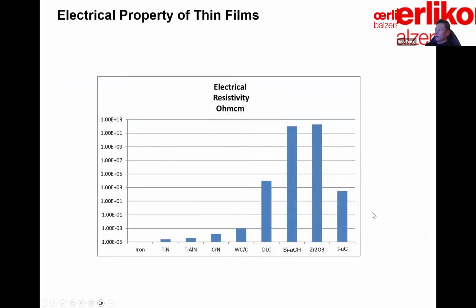Some of the tribological contacts are designed in an electrical field, or some of the surfaces are actually used for electrical applications, right? So that requires coatings with different electrical conductivities. We have titanium nitride, very conductive, close to the conductivity of iron. And we also have some options like the silicon doped ADLC that has dielectric properties similar to typical ceramics like zirconium oxide.